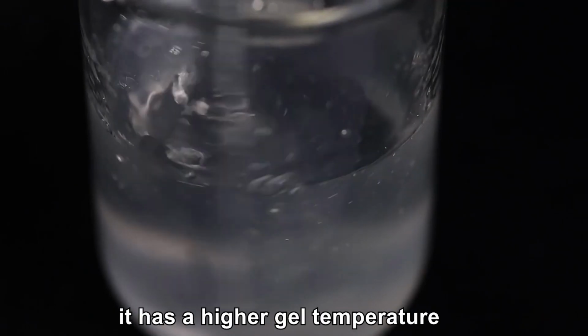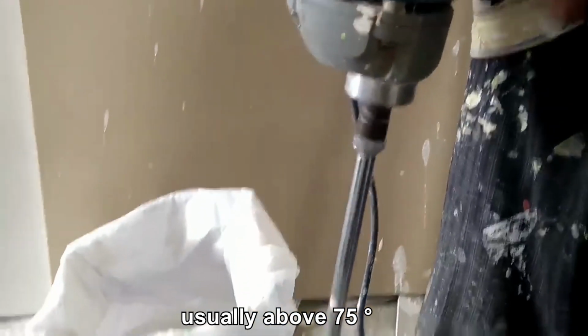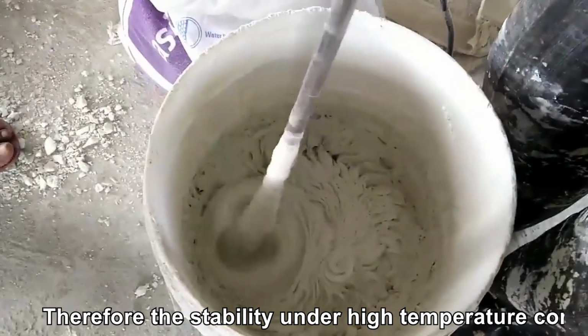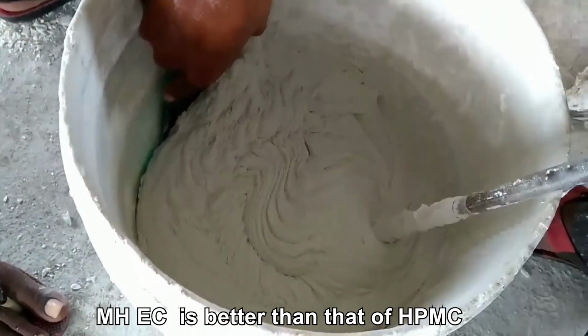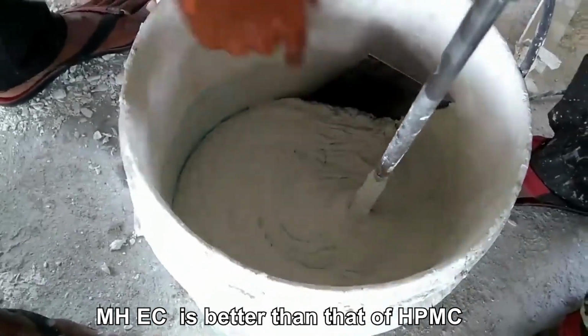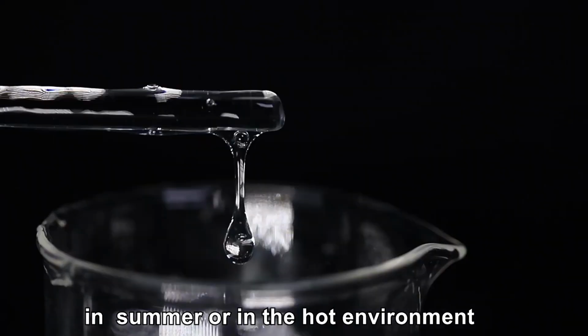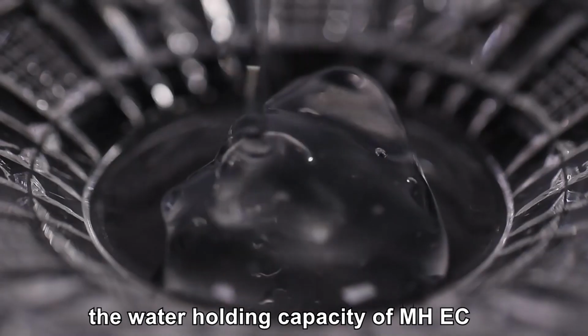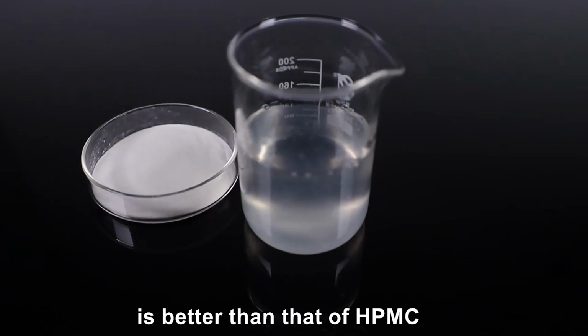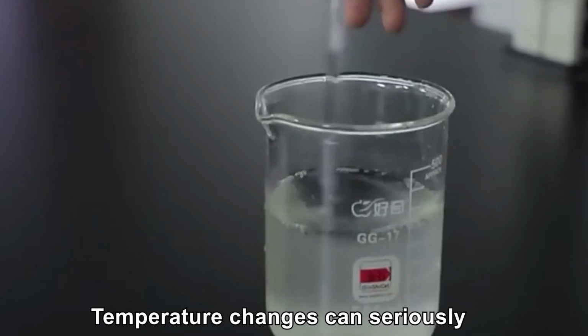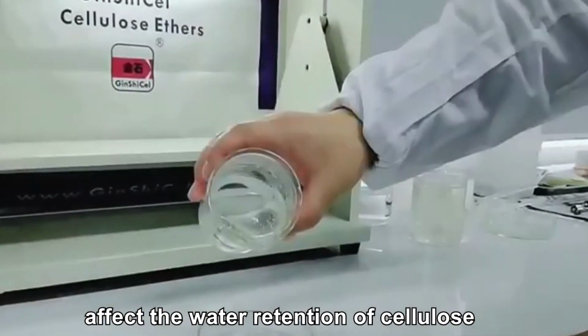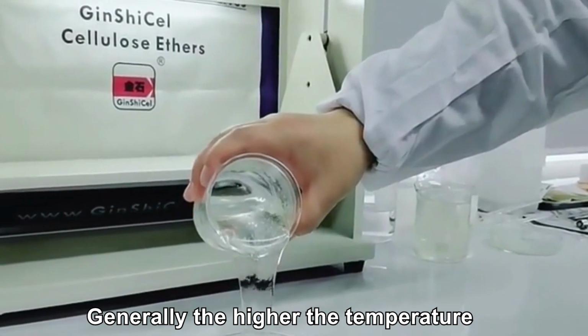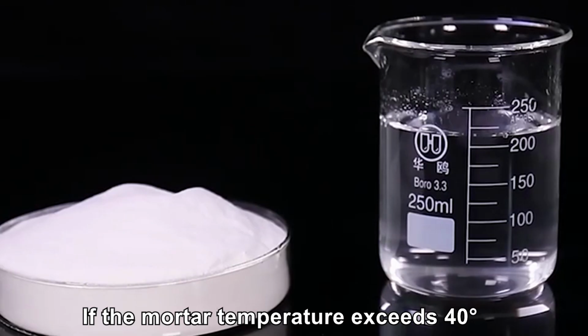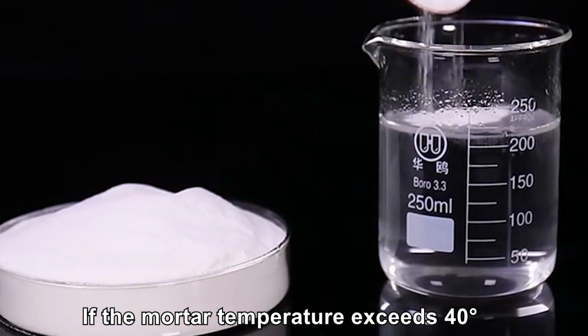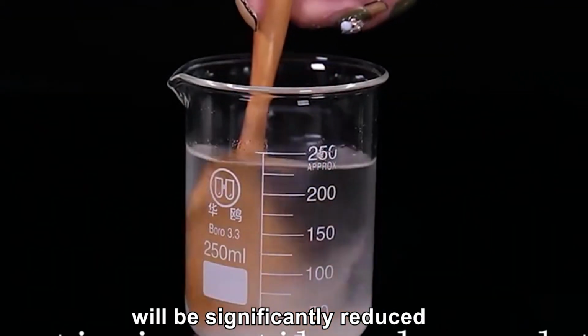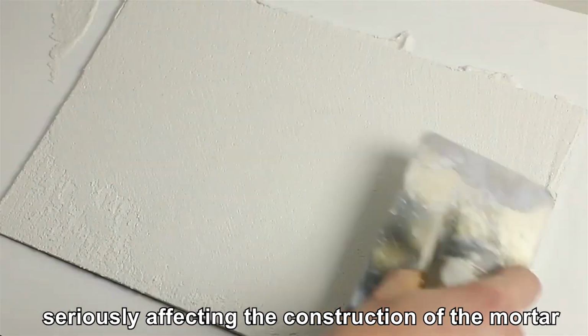It has a higher gel temperature, usually above 75 degrees. Therefore, for stability under high temperature conditions, MHEC is better than HPMC. In summer or in a hot environment, the water holding capacity of MHEC is better than that of HPMC. Temperature changes can seriously affect the water retention of cellulose. Generally, the higher the temperature, the worse the water retention. If the mortar temperature exceeds 40 degrees, the water retention of cellulose will be significantly reduced, seriously affecting the construction of the mortar.